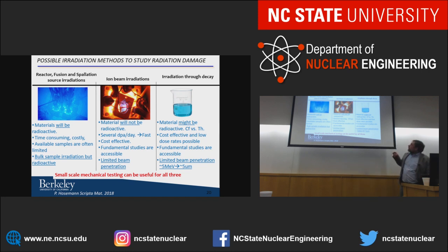Or if you're a nuclear chemist, you can have, for example, californium or so, which emits alpha particles of 5 MeV, and they travel about 5 microns into the material as well. Or if you're a molten salt person, the molten salt, of course, implants fission products into the surface of your pipe. And so you get surface implantation due to whatever radioactive liquid your material is exposed to. Now, all of these things have in common that either you have very limited penetration depth of your radiation damage feature, or that you want to keep the volume small because it's a radioactive material. And so we're trying to develop small-scale mechanical testing techniques to address the questions I posed earlier on dissolvable defects, non-dissolvable defects, to study these phenomena.